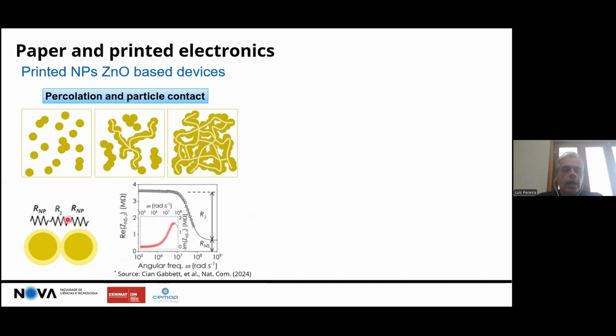Of course, the critical part is the contact between the particles, because the highest resistance introduced in the system comes exactly from this interparticle contact. You see here, by making a kind of frequency analysis, that the resistance of each particle is much lower than the resistance that you get from the interfaces between the particles. That is the critical point that governs the percolation of charges.